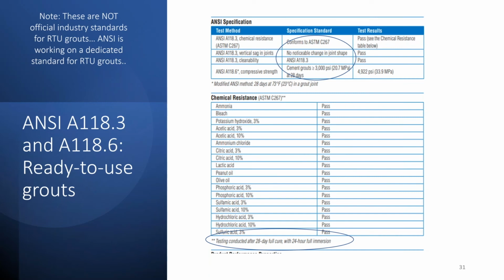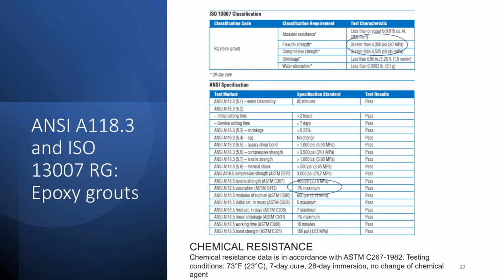The other thing to point out there is that we do pass, and that's why we use some of the epoxy and also some of the cement specs, with 118.3 and 118.6 for RTUs, pending their own spec. 118.3 and ISO, the key thing to point out here is now our water absorption's down to 1% or less. Impressive.